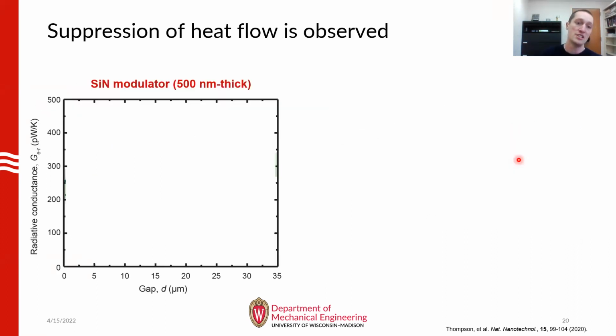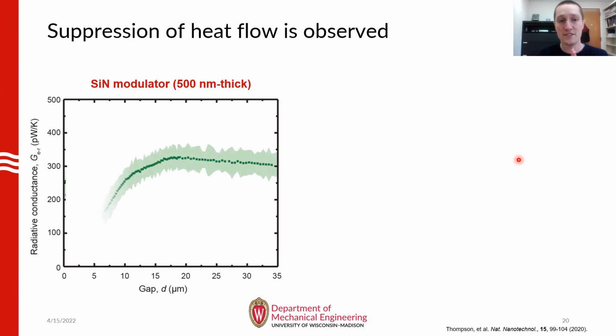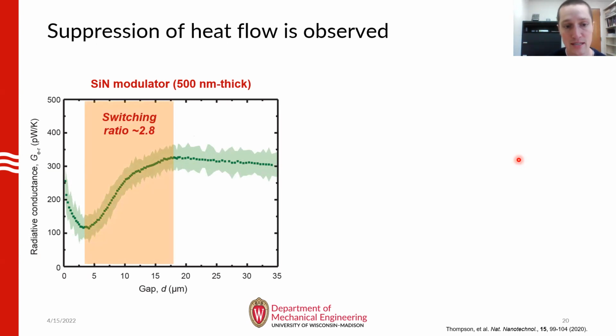So here you can see the central results of this experiment. Here, the radiative conductance between the emitter and the receiver is plotted as a function of that vertical offset. And here you can see that we essentially are able to adjust that offset in steps of 250 nanometers until contact. And basically, when we reduce the gap size from around 18 micron to 3.5 micron, we could suppress the radiative conductance by a factor of around 2.8.